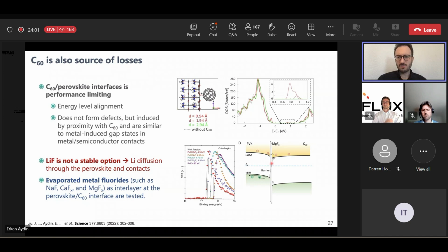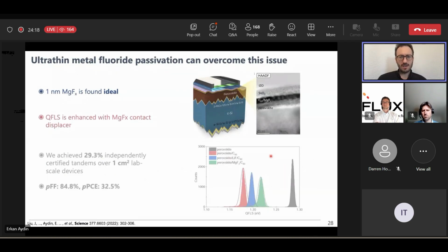And actually, it is really displacing the contact, and we are probably not forming a continuous layer. It's an ultra thin layer, around 1 nanometer, and this is allowing the tunneling of the charge at the contact. So in doing so, we minimize the voltage losses and we increase the quasi-Fermi level splitting of the perovskite subcell. And overall, in this work at that time, we reached 29.3% efficiency.